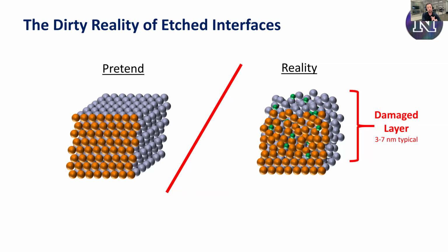Not great. There's a lot of evidence that RIE causes significant surface damage. Way back in 2006, people were looking at how the effective lifetime of a carrier decreases as the RF power of an etch increases. So the more energy you dump into the surface, the worse the carrier lifetime is. This is studied in a lot of areas. We know the higher the bias is, the thicker the amorphized layer is at the surface if you're just doing a simple argon sputter. Same thing, you put more chemical energy in, that damaged layer gets thicker. So, okay, well, what do we do about it?